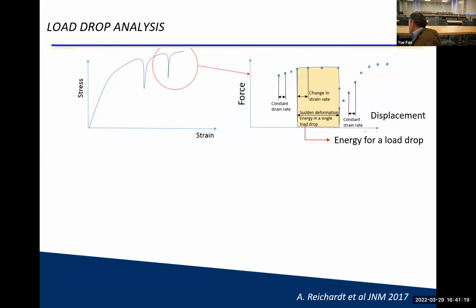So when we look at the load drops, what we actually look at is each data point, and when an event occurs, the spacing between the data recorded changes a little bit. So you can use it as a marker. At that point, you have a plastic deformation. And then you map out or calculate the area underneath the force displacement curve, which tells you how much energy went into this particular event. Force over distance is the energy associated with the load drop in my stress strain curve.